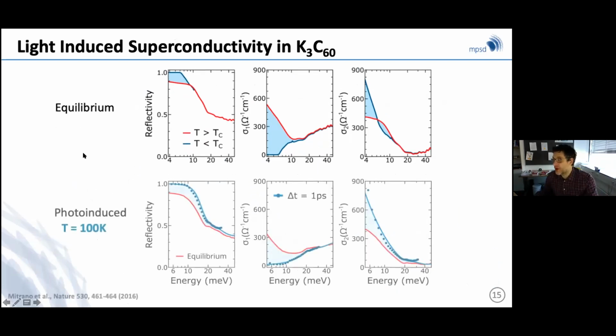And so one of the most striking observations that was pretty clear early on is that, at a pretty good quantitative level, one could go to 100 Kelvin, which is 5 times the thermodynamic transition temperature, pump a specific vibrational mode, and induce optical properties starting from the red metallic features and induce these blue metallic features, so reflectivity of 1 and opening of a gap, that are very similar to the ones that I obtain below TC. In particular, the divergence of sigma 2 seems to be pretty similar to the divergence that I get at 0 temperature, indicative of a delta function induced at 0 frequency that is approximately of the same size as the one that occurs when the system condenses by its own devices.